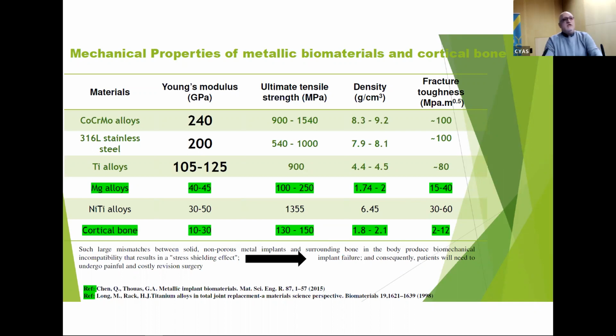Something like you are doing a load, you are putting the titanium or stainless steel over a bone, which is very light, so some kinds of pressure, and that leads to failure later. But the only material that closely matches the properties of bones is magnesium.